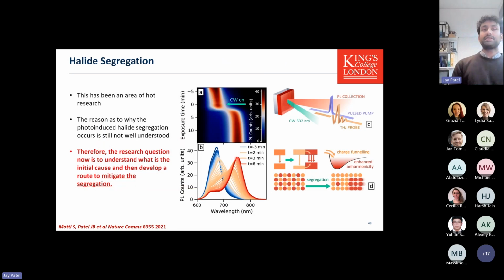Moving on, we actually looked at the physics of it, and it's currently a very hot area of research. We used ultra-fast lasers to see what happens to the intrinsic properties of these materials as the material is evolving and forming another segregated state. We find that because this other segregated state has a lower band gap, all of the electrons that you generate in the wider band gap material funnel in super fast into the lower band gap material, which emits. Now, this is a source of voltage loss, but it's not as bad as we think it is, because of this effect of the funneling, the amount of domains that actually form in terms of the low gap material is not that much.